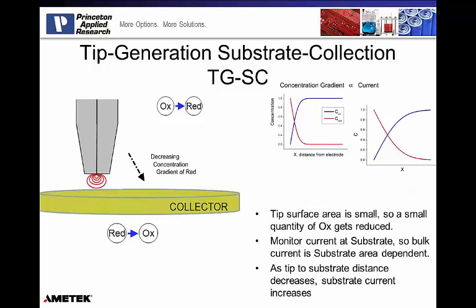I can run the exact same experiment in a different way, in tip generation substrate collection. The connections are exactly the same. All that happens is you redefine which one's generating the iron 2+ and which one's collecting the iron 2+. So in this diagram, the probe would be receiving the negative potential to reduce the 3+ to 2+. Now I have a concentration gradient propagating away from the probe that's going to be collected at the collector. So I'm going to see a constant current at the tip, and a change in current at the collector as the tip moves from an insulating into a conducting region.